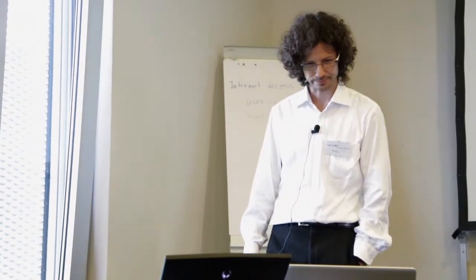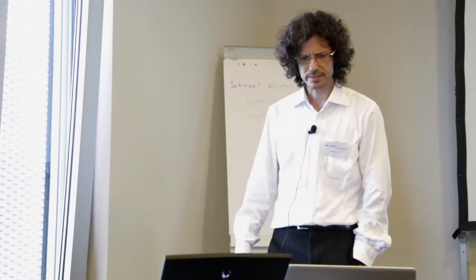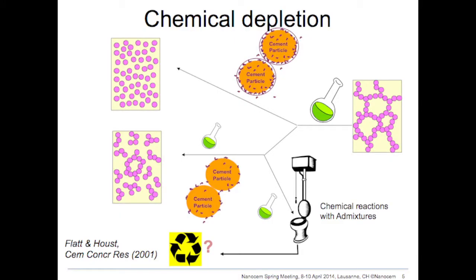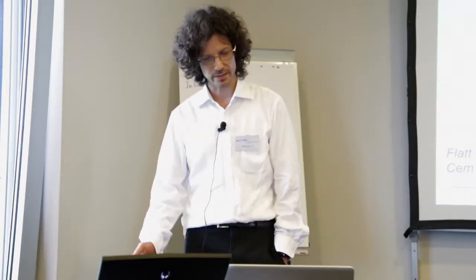So what's the simple picture that essentially we can use as a framework for thinking is that if you start with a flocculated system of particles that are sticking together in the concrete, the fine particles, you add a superplasticizer which adsorbs on the surface, disperses, and you get independently moving particles which can flow, and you get something which is more fluid, you can put less water, get higher strength, etc.